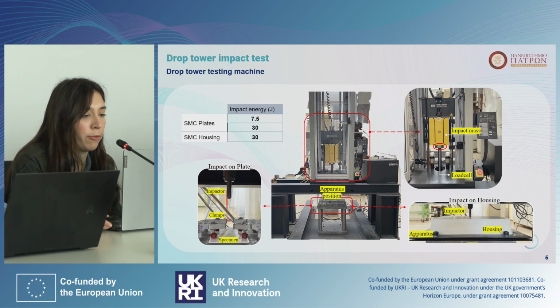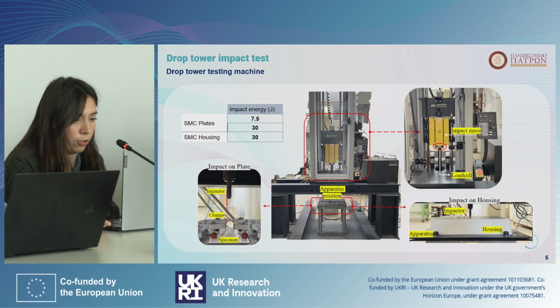The load versus time response is recorded for each impact event, and impact tests were performed at two energy levels, 7.5 joule and 30 joule for the flat SMC plates, while for the housing, testing was conducted at an impact energy of 30 joules. Following each test, the damage depth was measured at the center of the specimen, where the most significant deformation occurs.